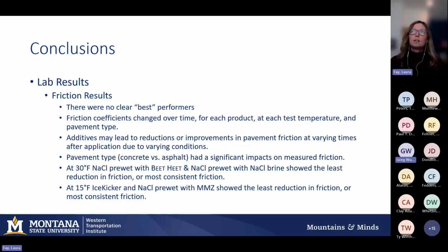But what's interesting to note is that for some of the friction measurements, the values were very consistent over time. So they had the least reduction in friction over time. And so at 30 degrees, that happened to be sodium chloride pre-wet with beet heat and sodium chloride pre-wet with brine, so the pre-wet control. And then at 15 degrees, the most consistent friction, or the least reduction in friction over time, was associated with ice kicker and sodium chloride pre-wet with MMZ or Magic-0.